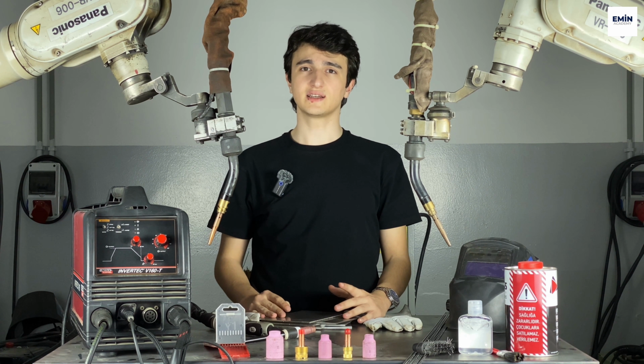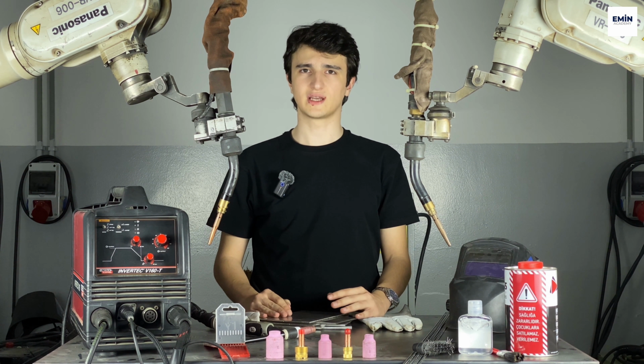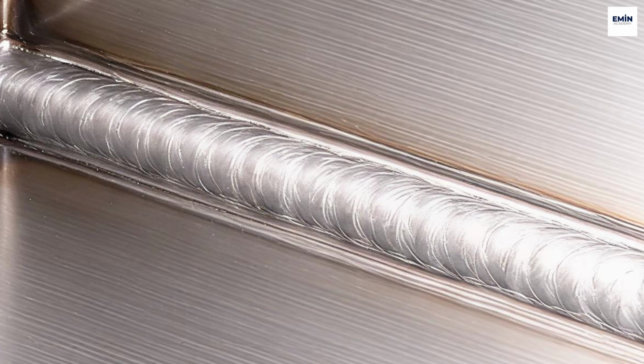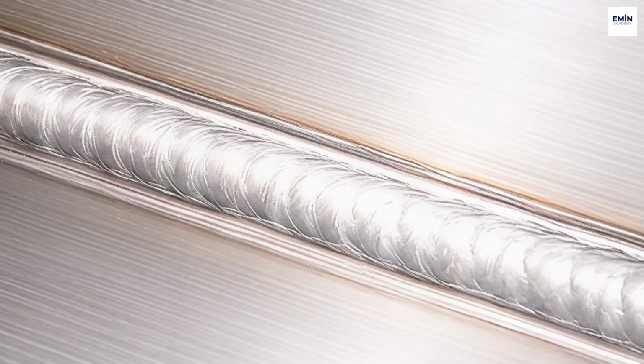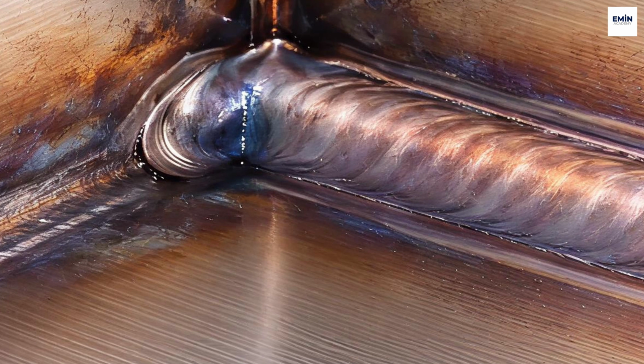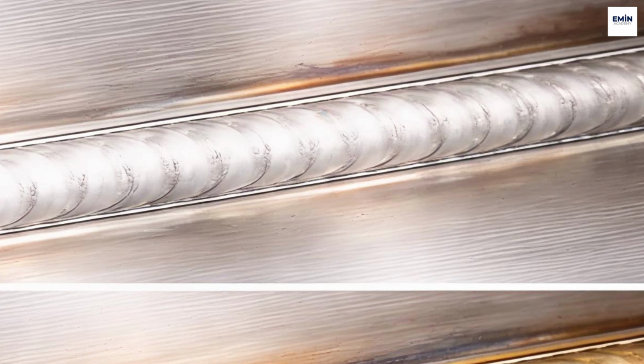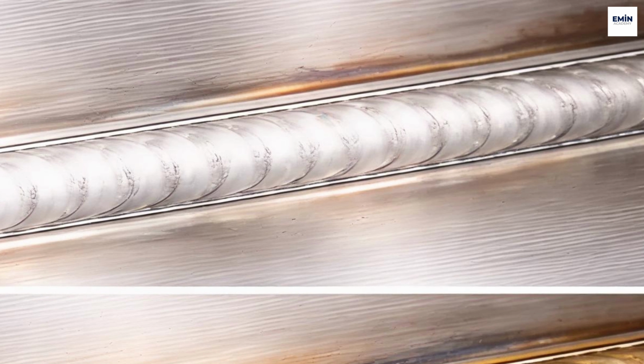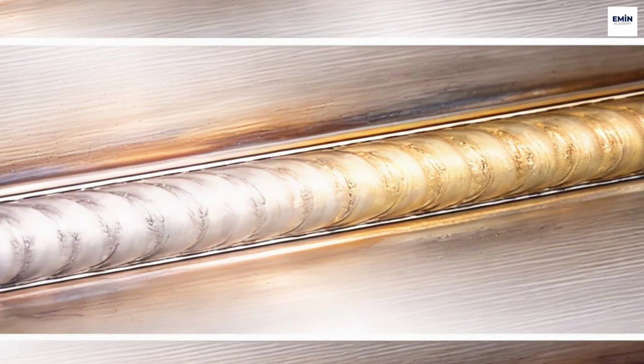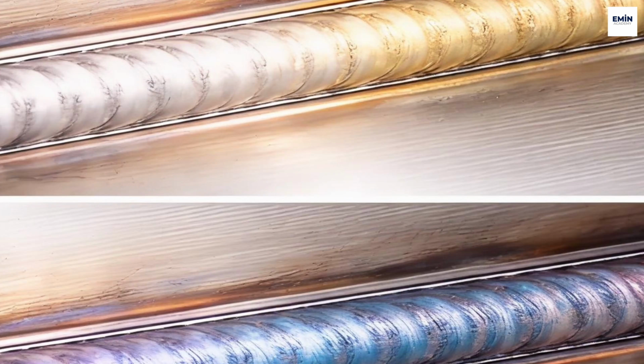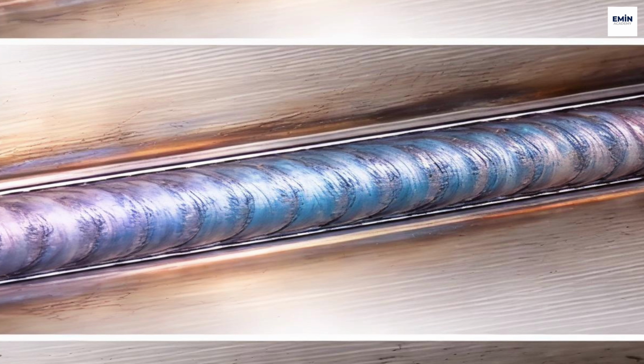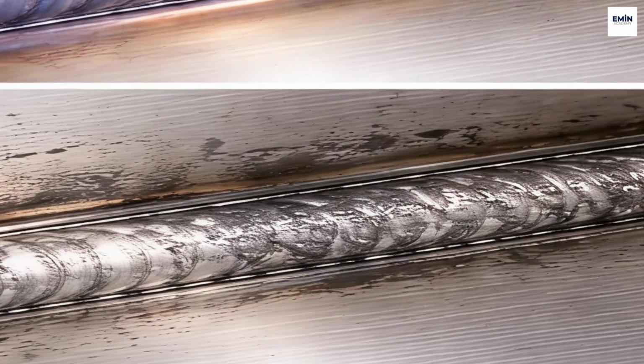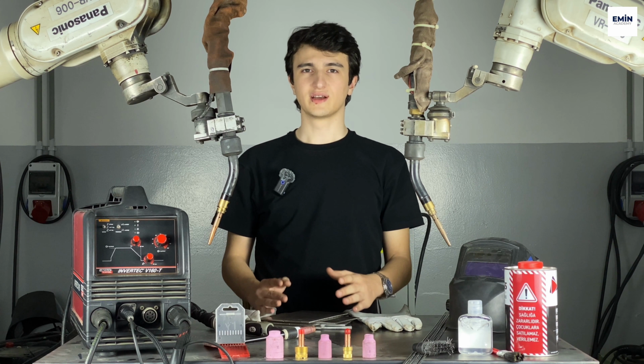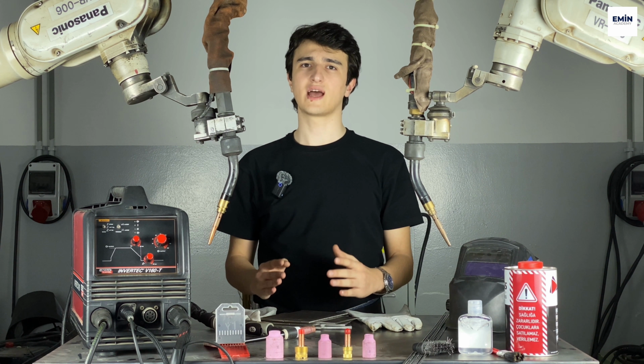In TIG welding, the color gives us very clear information about heat input and gas coverage. If the weld pool is properly shielded and the heat is under control, the weld will be light in color. But if oxygen or excessive heat comes into play, the color will darken. The meaning of weld colors: silver, light gold: a perfect weld, proper gas coverage, and ideal heat. Light yellow, light blue: slightly too much heat, but acceptable. Dark blue, purple: excessive heat. The amperage is too high, or you're moving too slowly. Gray, black: there's oxidation, the gas coverage is insufficient, or the surface is dirty. Remember, the darker the color, the more oxygen the weld has been exposed to.